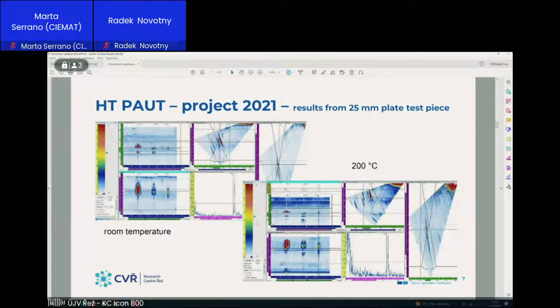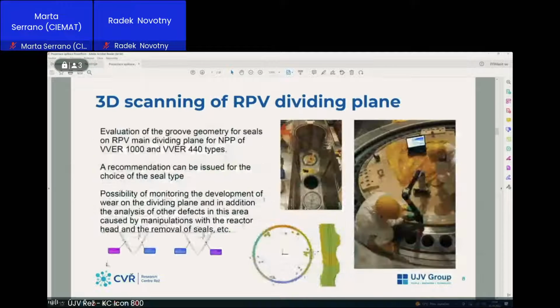Here are similar results which you could see for temperatures up to 350, detectability and sizing was okay, and nowadays we have two qualified inspection procedures, and we are in the state of preparation of demonstration of measurement in situ. So it means in technology of secondary site of Temelín NPP.